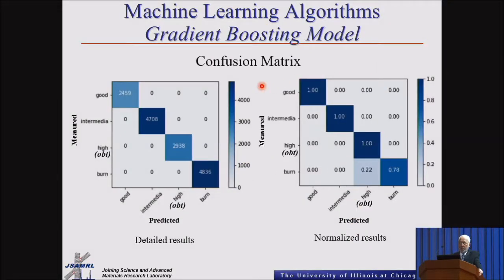This is another way to present the data, using the confusion matrix. For the gradient boosting, we take a look at the measured and the predicted, both in the detailed results as well as the normalized results. In all cases, there was pretty good agreement between the measured and the predicted. The only problem was when it came to burn through. As I mentioned, burn through is a transition that is difficult to make a good assessment on.